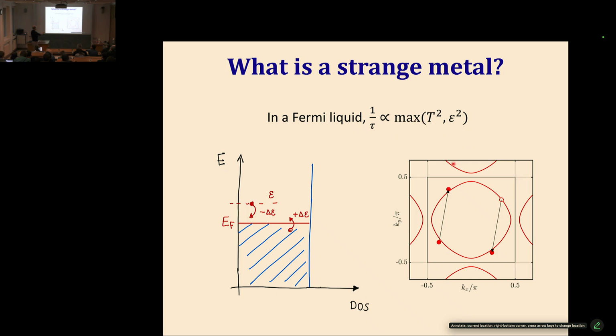So could there be a caveat to the argument there? Typically, there wouldn't be. Typically, you would say the relaxation time of the current, if anything, could be much longer than that of a single quasi-particle, meaning the scattering rate of the current can be much smaller than that of a single quasi-particle. For instance, if we didn't have umklapp scattering, we can still relax single particles, but not the total momentum of the system. So we don't expect quasi-particles to live longer than the current. If anything, they live shorter. So it's an upper bound.